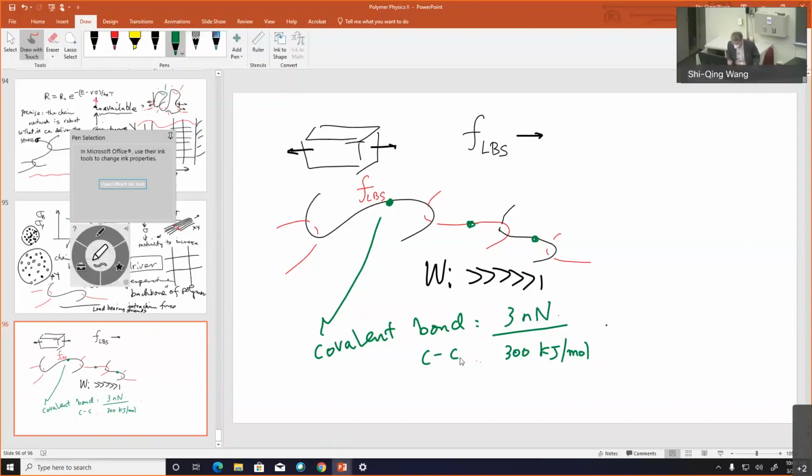So, okay. So the story is, as we're saying, I know I'm skipping a lot. As I keep drawing, this force potentially keeps building. I'm asking you in this depiction, where is the weakest link? In other words, where will be a mechanism or a spot where the force will be unable to grow further? The chain tension. And I was trying to clarify, it's not coming from breaking the bond. The bonds are quite strong. So that left with only one answer, which I already revealed. Right?